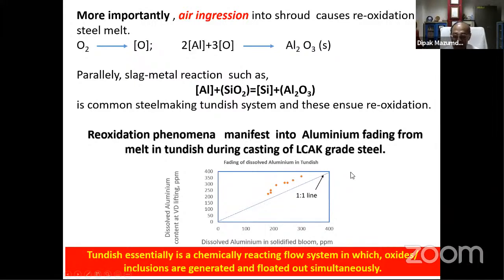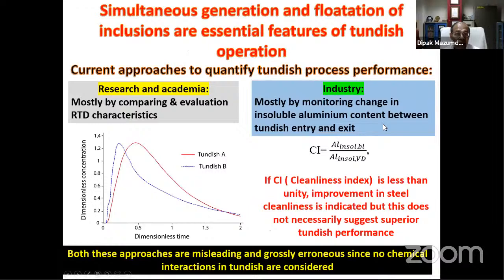I think we are in the 21st century, where steelmaking is 160 years old, and it is perhaps time to take into consideration the exact nature of the reactor in order to deliver what is required to be delivered. Now, most of the time, we as academicians compare Tundish designs by the residence time distribution curve, where we inject a dye, find its residence time distribution, get it done for two different Tundish designs, and then we consider, by evaluating these curves, which Tundish has a better inclusion flotation capability. But this is not right, because it does not capture one of the intricate features of Tundish operation, which is reoxidation. So my assertion is that you can get a rough idea, but this nonetheless is not going to be the true picture, or it can be misleading also in some cases.